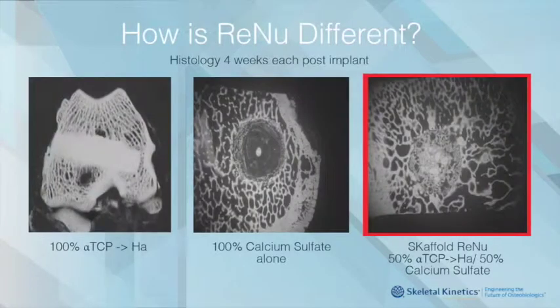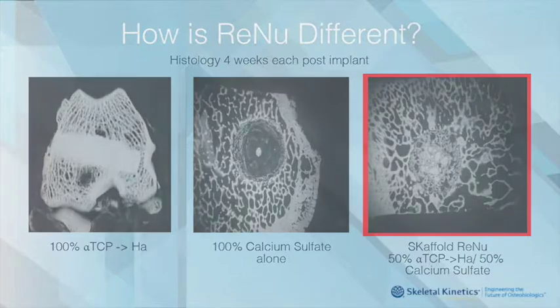On the left-hand side, we see the pure alpha-TCP at 4 weeks. In the middle picture, we see a pure calcium sulfate at 4 weeks. And at the right, you see the result of combining these two grafts. What remains is a 50% macroporous, interconnected hydroxyapatite matrix, which will allow for faster remodeling.